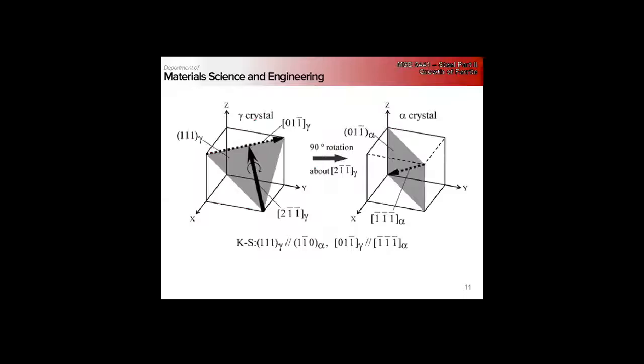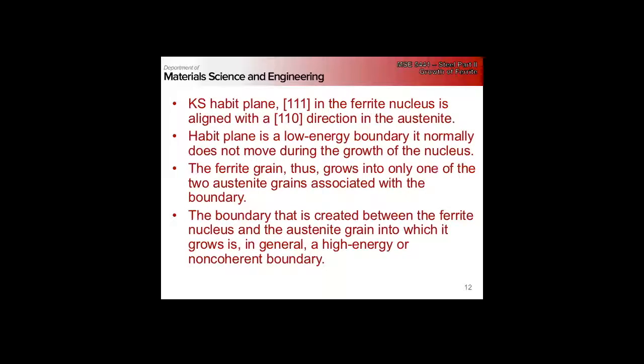So this relationship is formed with one of the two austenite grains, and then our ferrite will grow into the other, leaving this relationship fixed. The boundary between the ferrite and the austenite grain into which it's growing is generally going to be a high energy or non-coherent interface.